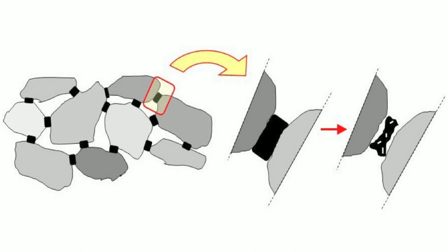But we have a solution. Here you see how the damage appears in this material. It's a porous asphalt, like I said, so you have only a small amount of binder between the stones. Due to weathering, UV light and oxidation, this binder, this bitumen, the glue between the aggregates, is going to shrink. And if it shrinks, it gets micro cracks and it delaminates from the aggregates. And then if you drive over the road, you take out the aggregates, what we just saw here.